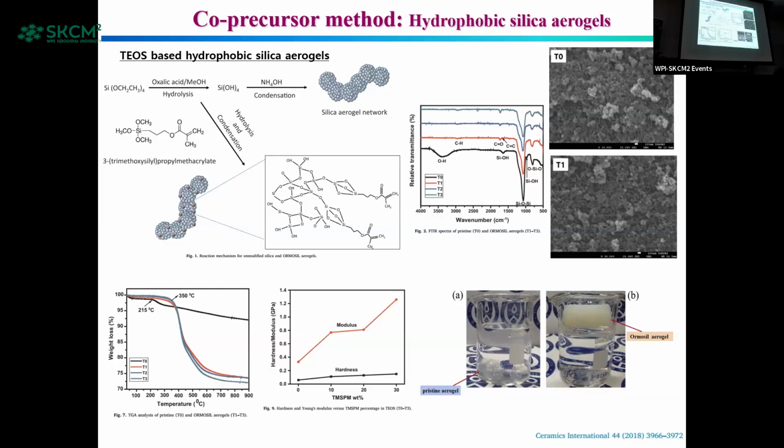And we achieved a hydrophobic aerogel after this modification, because the pure pristine aerogel is hydrophilic, so it settles down in the water. But the Ormosil aerogel we prepared, the organically modified aerogel, sustains on the water surface. So it is hydrophobic.